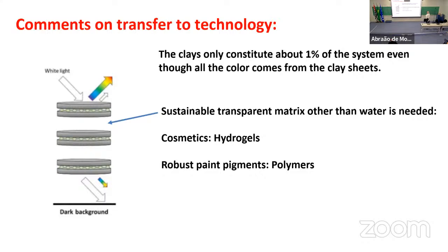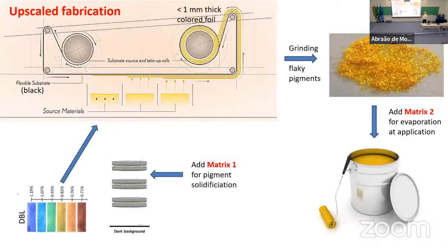And we solve this problem because our form factor is in the X-ray range because of the thin platelets. Our structure factor is in the color range. So how do we get to industry from this? What we have to do is to replace the water with a stiff matrix, something that is solid and transparent. So that's what we're looking for now. That's the stage of development where we are now.